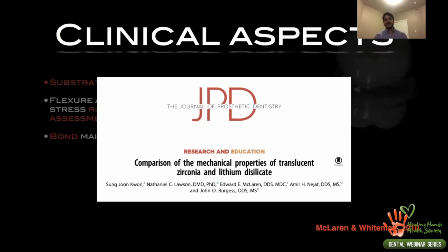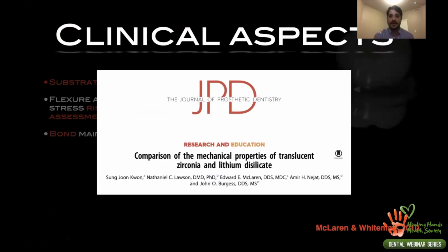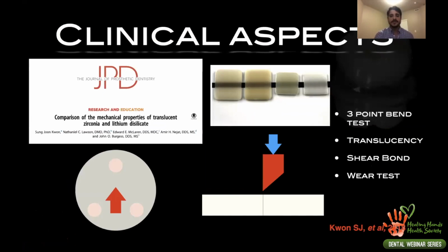This article from the group from Alabama, just published in 2018, evaluated flexural strength with the 3-point bend test. It evaluated the translucency and the bonding to lithium disilicate, translucent zirconia, and conventional zirconia. And the results summarize what we discussed.